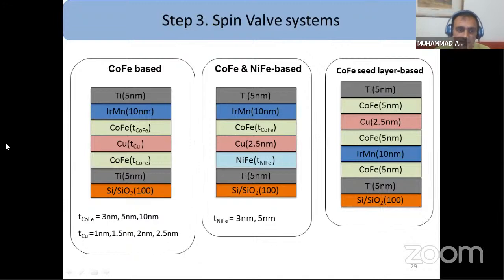Step 3 is the production of different spin valves based on cobalt iron and nickel iron, with a cobalt iron seed layer base. For the optimization of the MR value, I have changed the thickness of the ferromagnetic layer and the non-magnetic copper. The cobalt iron thickness was chosen as 3, 5, and 10 nanometers in each case. Similarly, the cobalt iron based and nickel iron layer, with cobalt iron as a seed layer.